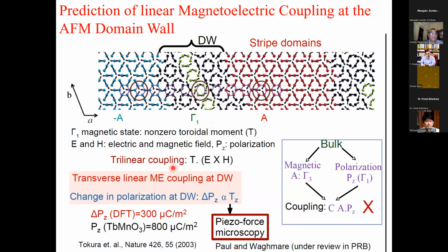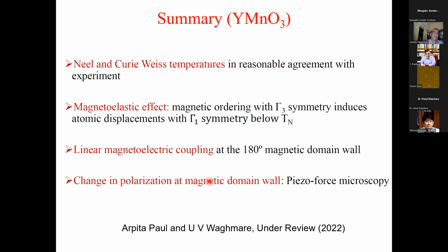can have trilinear coupling like magnetoelectric coupling, which involves coupling between electric field and magnetic field and this toroidal order of spins. So this is a theoretical prediction that indeed you will have transverse linear magnetoelectric effect at the domain wall. And that's something that will be measurable using piezo force microscopy. So if you take a piezo force microscopy tip across the domain wall, you should see interesting changes in magnetic moment and electric dipoles too.